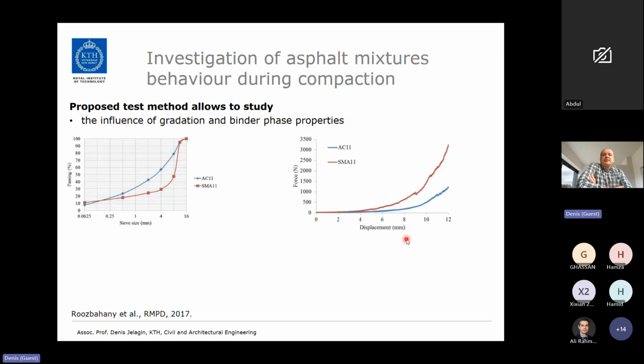Here you have one example of this vertical force displacement relationship for asphalt concrete and SMA with same maximum aggregate size. And as you can see, SMA requires significantly more force, which is kind of expectable due to kind of gap-graded nature, as compared to asphalt concrete to achieve the same level of compaction.